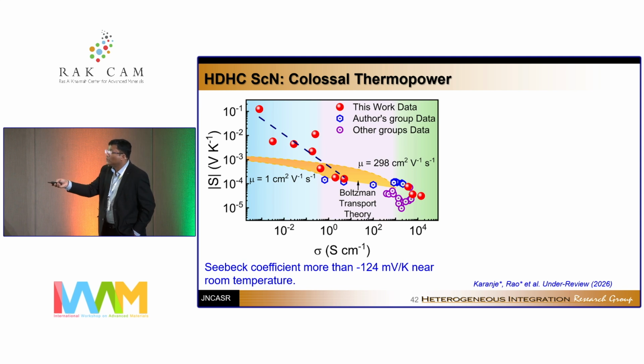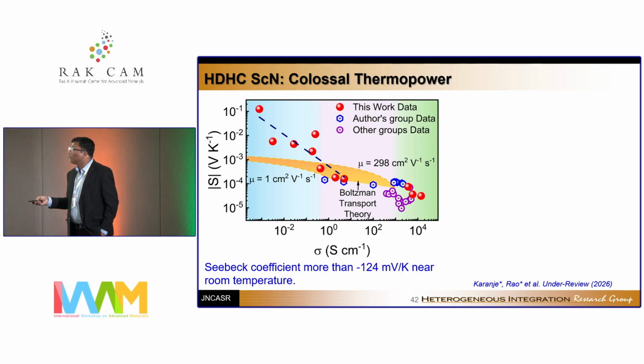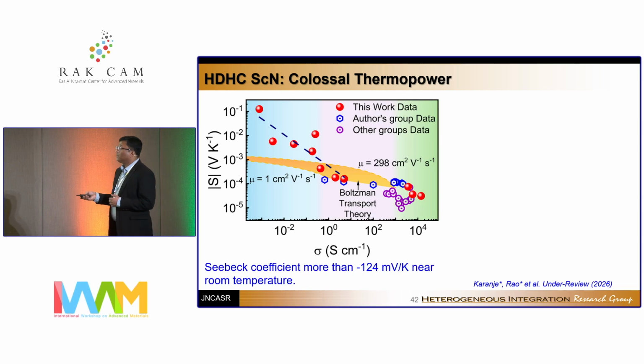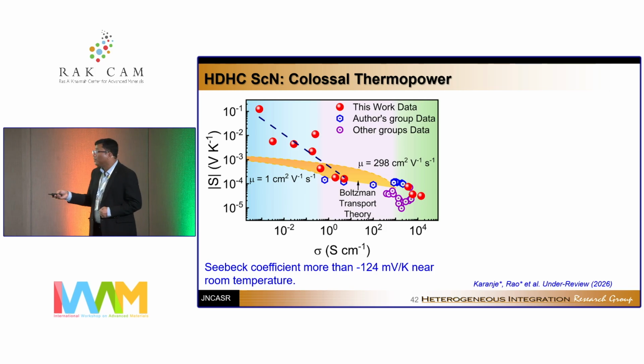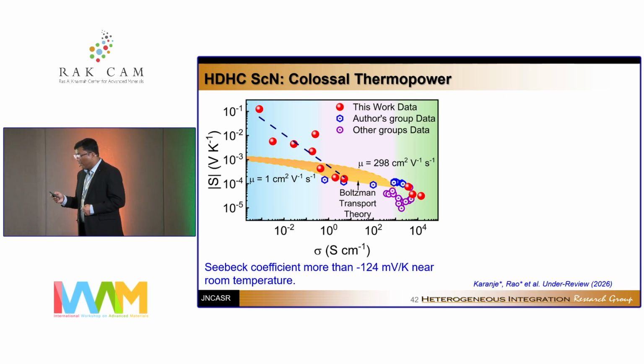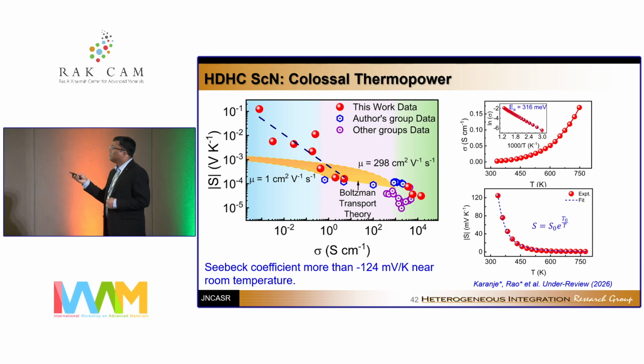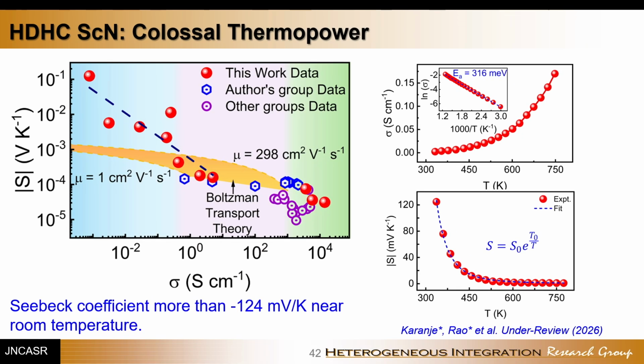But as you reduce the conductivity by hole doping and create the potential fluctuation, we have reached a Seebeck coefficient of around 124 millivolt per Kelvin, which is something people have seen in some organic materials like C60, but for inorganic semiconductors, this is probably one of the highest reports of a Seebeck coefficient in any type of material. We also looked at the electrical transport details in terms of conductivity versus temperature and Seebeck coefficient versus temperature, and I'm really happy to talk about it later if you are interested. So with that, let me end.